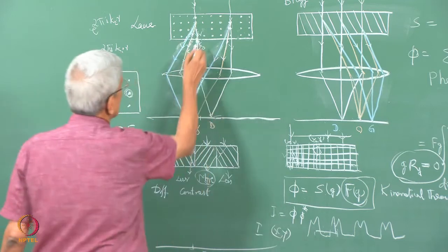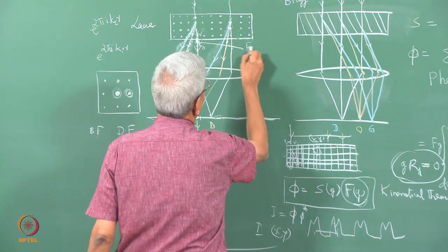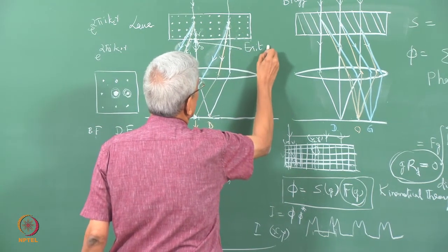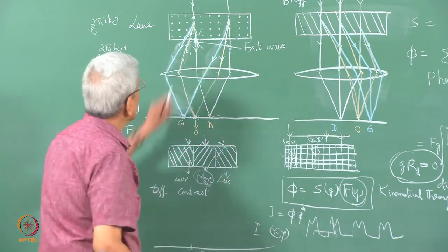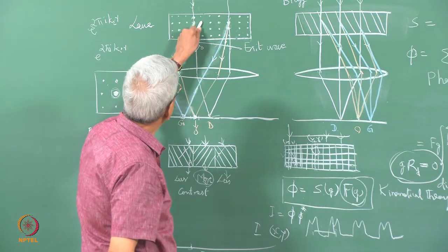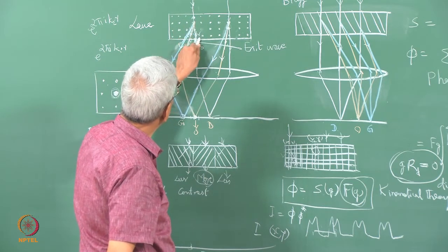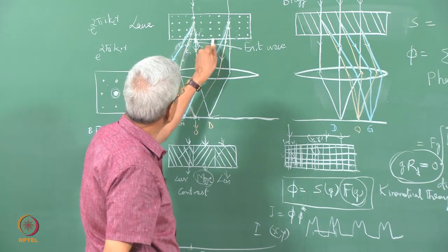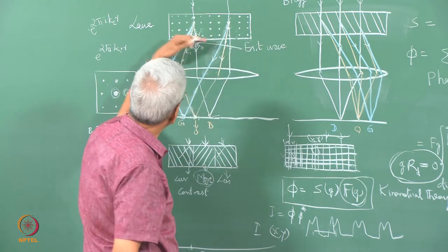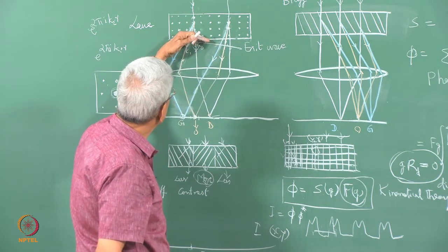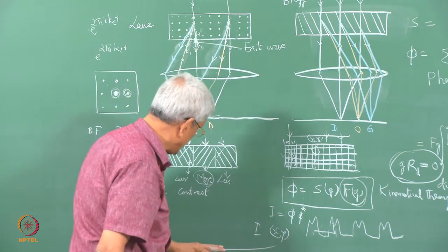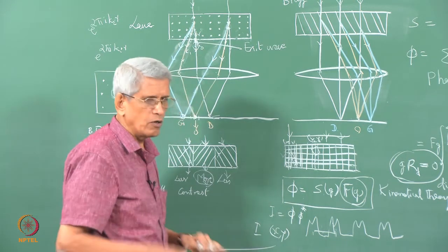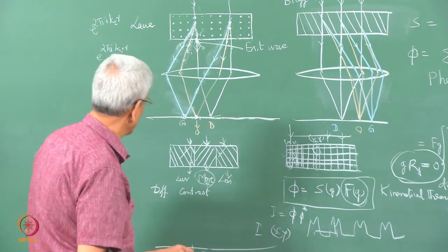This wave is called the exit wave. Depending upon the scattering which takes place at different points, it will vary from region to region. The image of this exit wave is what we are seeing as the image in high resolution microscopy.